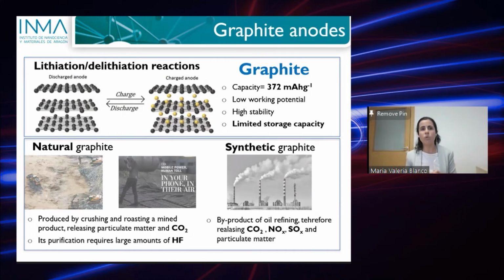So graphite anodes have a storage capacity of 372 milliamp hours per gram, which worked well in the past, but is not enough for next generation lithium-ion batteries. But the good thing about graphite is that it's quite stable. And this is because during the charge and discharge, the 2D host structure of graphite, as you can see in the picture, will move to allow the insertion of lithium ions between these layers. And in the discharge, this space between the layers will change a bit. But the change is not so big, so there is not much structural damage to the host structure during charge and discharge, and that's why graphite anodes are very reliable.